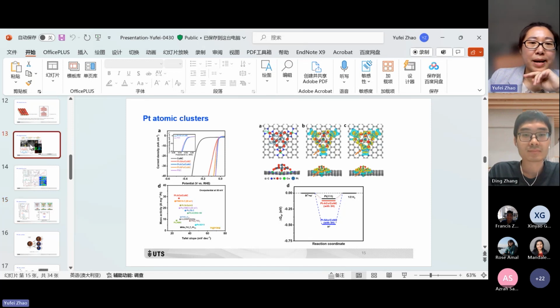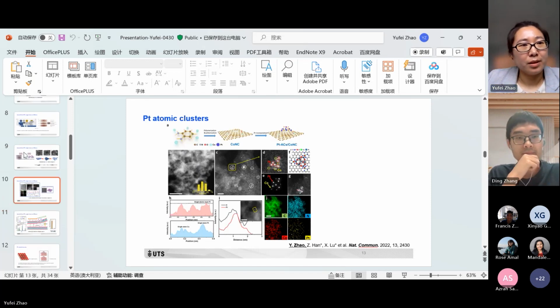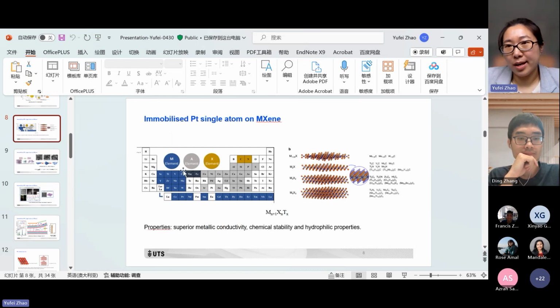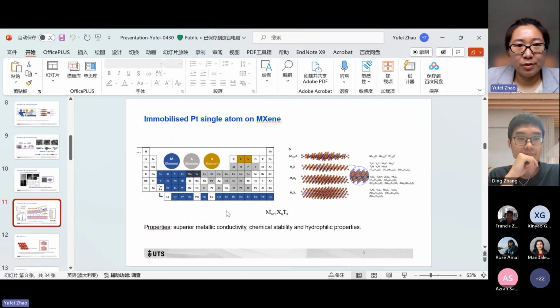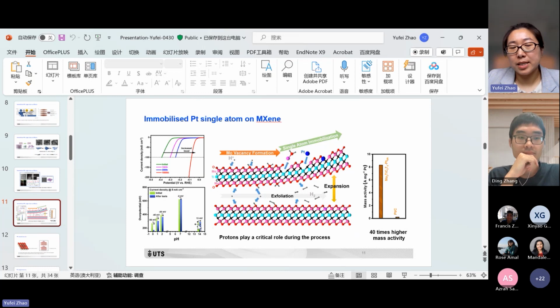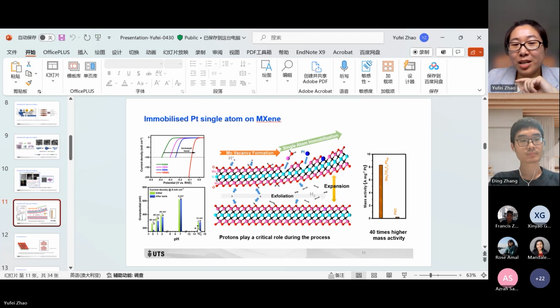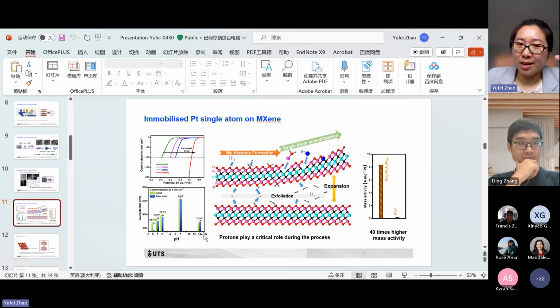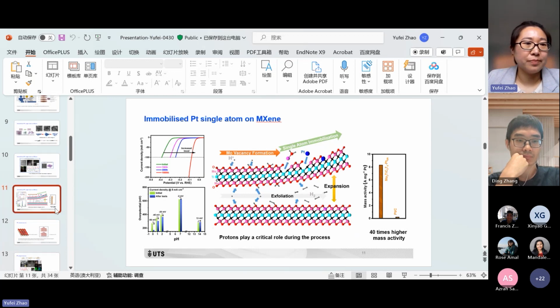For the MXene-based one, it's not good in alkaline conditions. Even though we only tested the MXene, with no single atoms, we can see in the alkaline condition it is not that stable, especially when we increase the concentration of the alkaline solution, it will react with the alkaline. So for the MXene, I think it's a good catalyst in acidic conditions, but not in alkaline conditions.